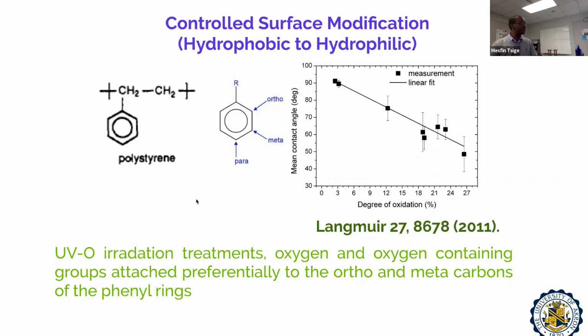So they came up with a way of doing that. What they did was irradiating the surface of polystyrene with UVO treatments changes the surface from hydrophobic to hydrophilic. The way that's done is the ortho and meta groups of polystyrene become oxidized. So oxygen-containing groups are tied to the phenyl rings, and that makes the polystyrene surface hydrophilic.